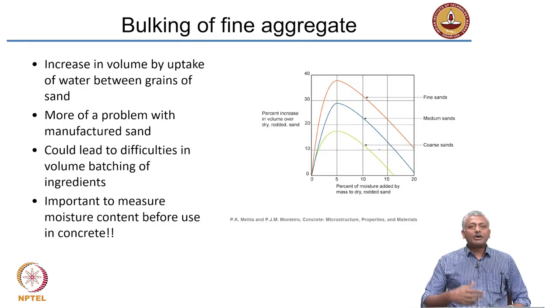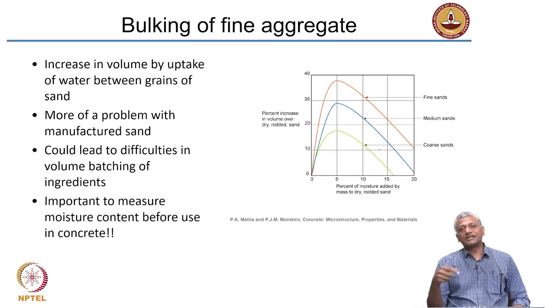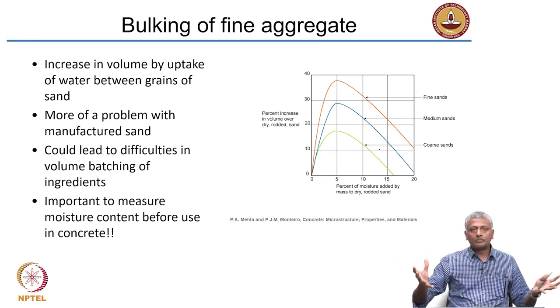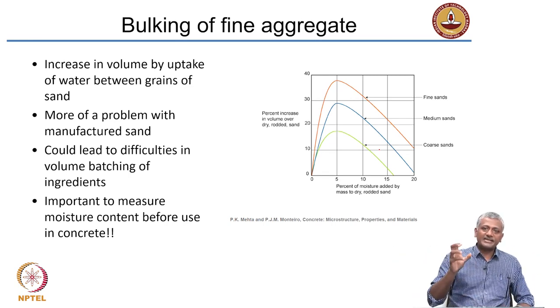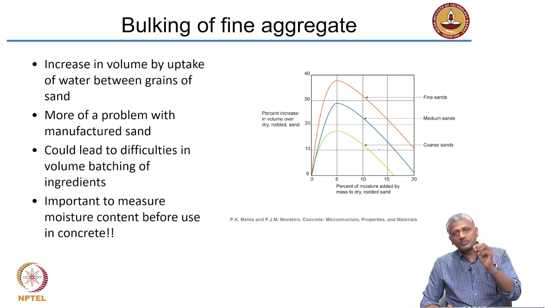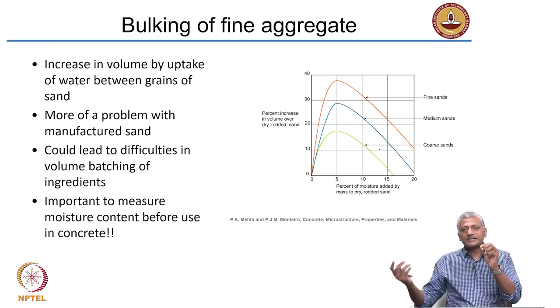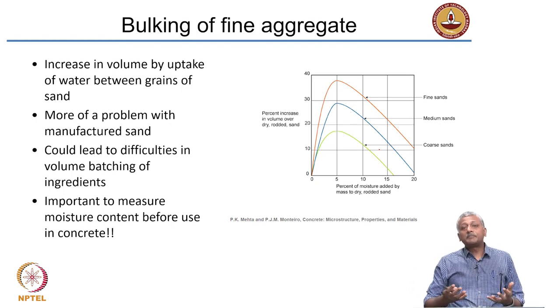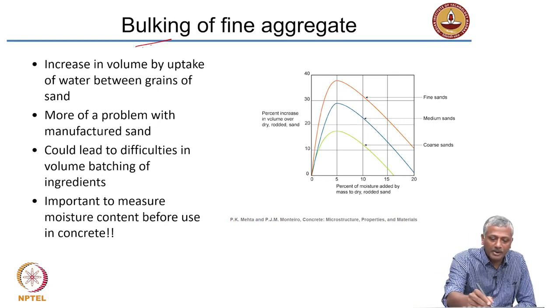As we already discussed, stone starts absorbing moisture and then there is a film of water clinging to the surface. With sand, if you take a look at sand as a volume, fine sand is usually packed with small voids inside. As it absorbs moisture, water goes in and expands the void present between the sand grains. As a result, the sand appears to be larger in volume than it actually is — that process is called bulking.